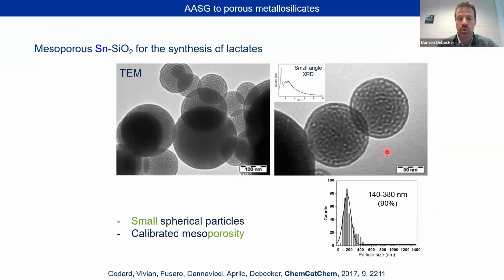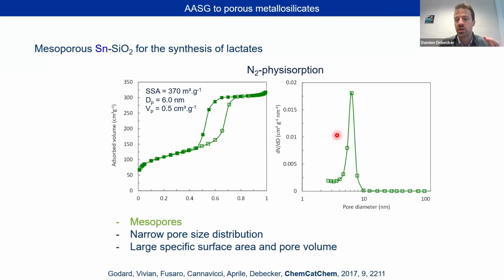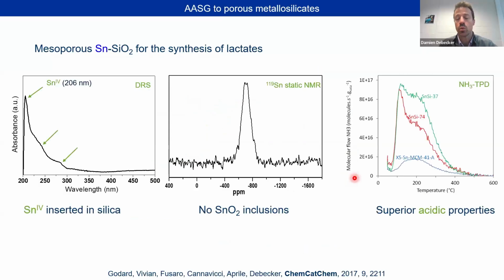So how do they look? Well, they look like this. We have spherical particles, of course, because they come from spherical liquid droplets. They're quite small, centered here on 200 nanometers, so that's nice. And you can already see the calibrated porosity here in these TEM images, which is perfectly confirmed by nitrogen physisorption. You see here the mesopores centered clearly on about 6 nanometers. So okay for catalysis.